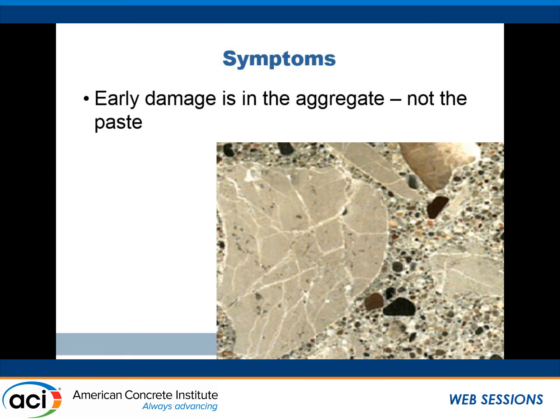Somebody was asking a question, how do we tell if it's an aggregate or a paste-based issue? To my mind, it's pretty simple. On the outside, Tom already referred to it, or maybe it was Randy, the cracking format is slightly different. If it's an aggregate-based issue, it tends to spread further and further away from the joint. If it's a paste issue, it tends to move a little bit more slowly. But really, the fundamental test is cut it in half and put it under a microscope. If the cracks are in the aggregate, it's an aggregate problem. If the cracks are in the paste, it's a paste problem. And if you want to learn about that one, you've just missed a really good session two doors down.